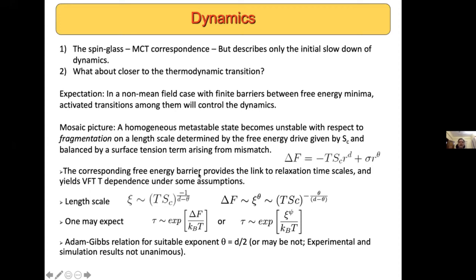And if one says that the relaxation time is governed by, I should have put a star on these delta f's in the latter equations, but if one says that the relaxation times are given by a free energy barrier divided by kBT, or if one were to say they're governed by the length scale raised to some power in the exponential, with suitable choice of these theta and psi exponents, one recovers a form of the relaxation times' dependence on the configurational entropy that looks like the Adam-Gibbs relation.